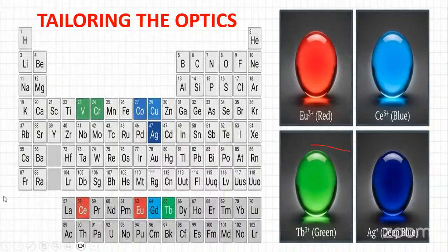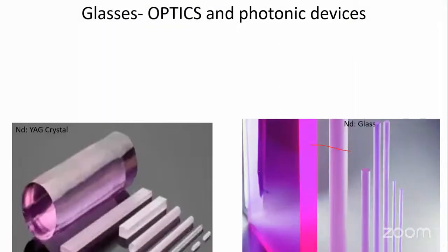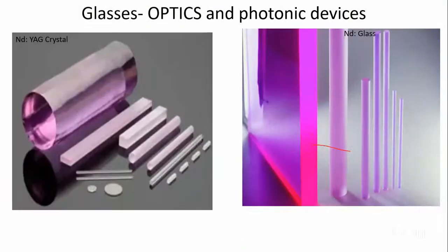See, all these elements, that is 3D transition elements or even the 4F transition elements that are present here, and even the noble metal nanoparticles that are present here, they can be used as the dopants. So if I use europium, I can get some reddish color. If I use cerium, I can get bluish color glass. Then with silver, I can get bluish color glass. So that's how you try to come up with glasses.